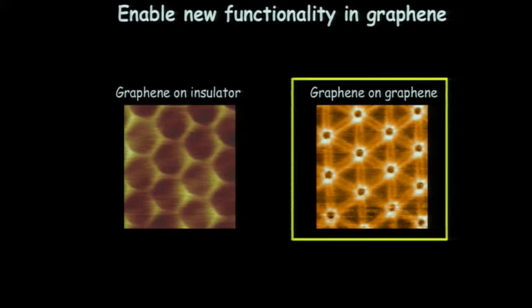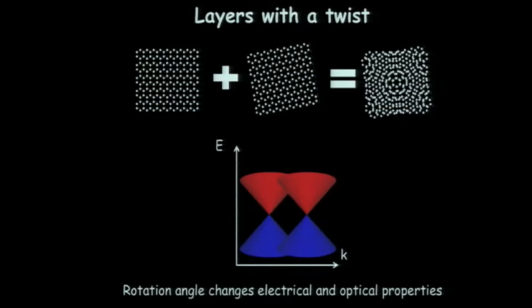So the other story that I wanted to tell you was what happens when you do graphene on graphene. So as you probably know from Pablo's work, when you take the 2 layers of graphene here, you put them with a twist angle between them, you can change both electrical and optical properties. Right? You're just basically changing in K-space where these cones are, and if you get them close enough together, you get these flat bands and you get superconductivity at 1.1 degrees or so.